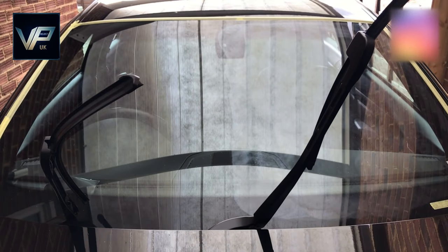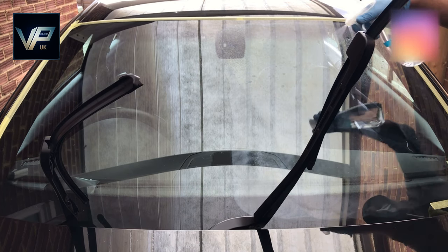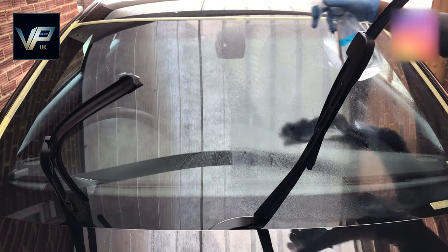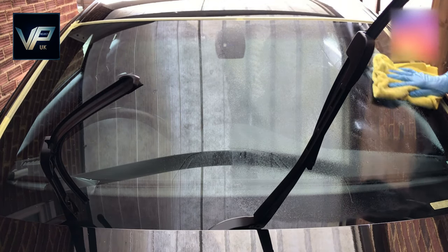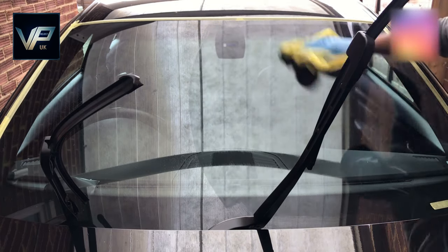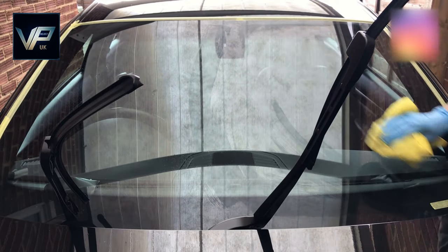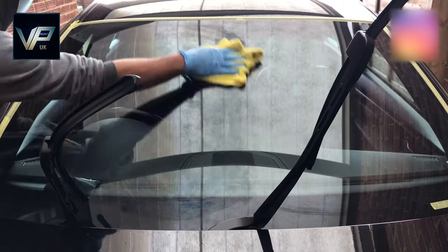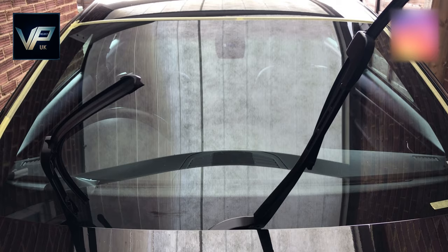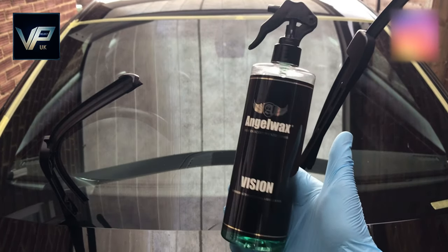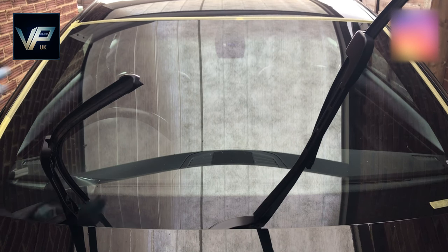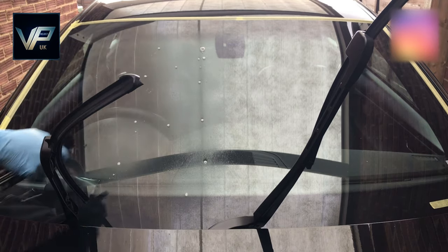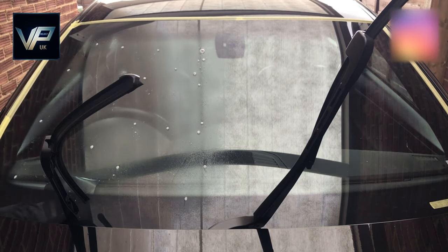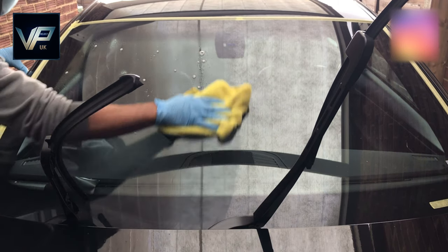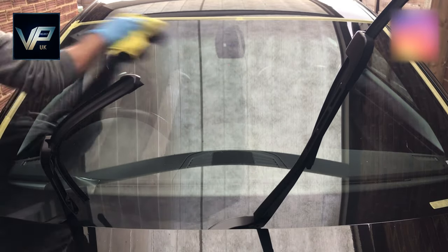Once you finish machine polishing, spray some distilled water again just to make removal of cerium oxide much easier. As glass is a lot harder than your vehicle paintwork, you can actually machine polish it numerous times. So off camera, I machine polished the glass a further 2 times, totaling 3 times in total, just to remove as much of the scratches as possible. And it was actually quite successful. It wouldn't have shown up on camera, so I didn't bring the camera in too close to show you. But it did have really good results.